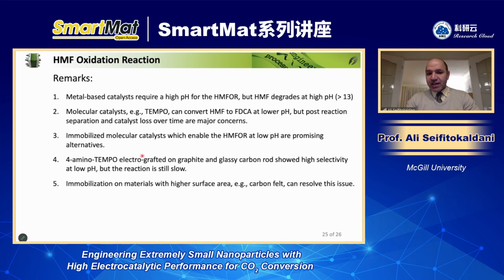And electrografting is the procedure that we followed. But the reaction is still slow, and we know that we need to work on how to increase, let's say, the turnover frequency on the immobilized catalyst. So immobilization on material with high surface area, such as carbon felt, can resolve this. If you use a high surface area carbon felt, then you can run the reaction at a faster rate and then achieve higher conversion.